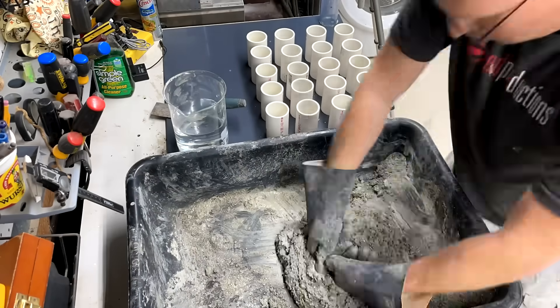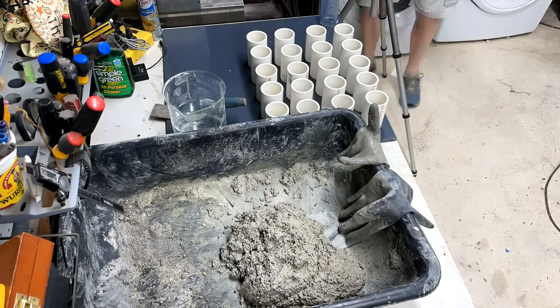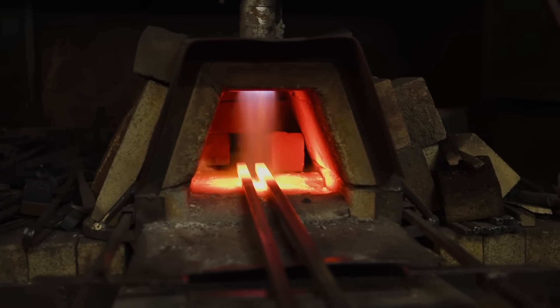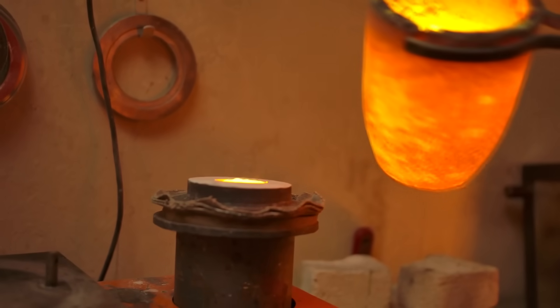Interestingly, once the concrete is broken, it sometimes carries a sign that it got too hot. Many of the aggregates used in concrete will turn pink after exposure to extreme heat — you can see that most of the rocks in the heated sample are pinkish compared to the control cylinder. Refractory concrete isn't a single material, but really a general name for concretes designed to withstand high temperatures. Every manufacturer has their special blend of herbs and spices. Usually they use cement that includes oxides, which absorb heat less readily and have reduced thermal expansion, so they're less prone to deterioration when subjected to extreme temperatures. They also have embedded fibers that provide insulation and tensile reinforcement, similar to the way rebar holds macroscopic cracks from growing. These extremely useful properties are taken advantage of in a variety of industrial processes like furnaces, kilns, incinerators, and even nuclear reactors.